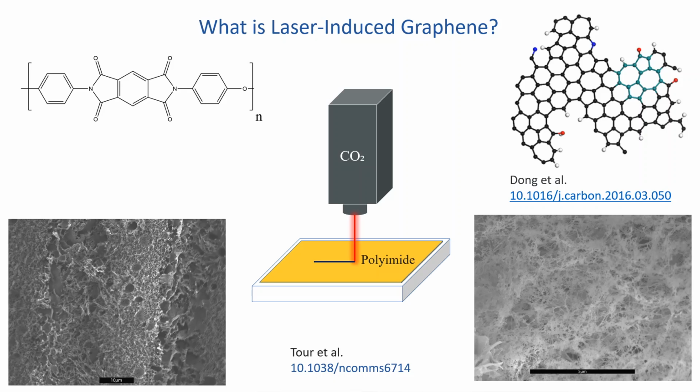As can be seen from the SEM micrographs here, the resulting material can range from highly porous all the way up to web-like strands, depending on the formation conditions used. These complex three-dimensional structures are a product of the complex formation process and the presence of Stone-Wales defects in the sheetlets allowing for curvature, not normally expected from graphene-like material.